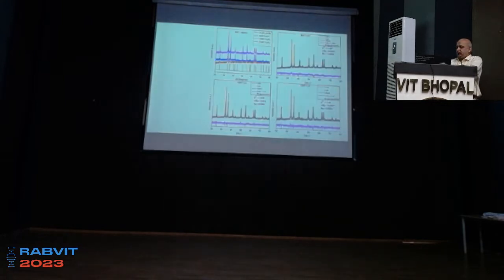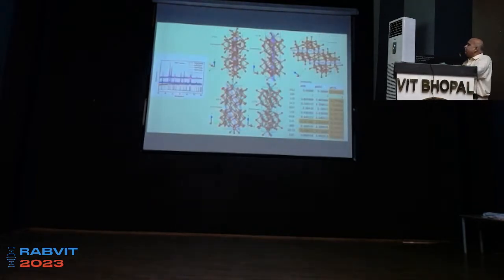Now, so this is the exciting part. Okay. So we started putting our mind into what exactly is different in S10. And what we found is that the different planes have different intensities. So what is the change between one sample to the other in terms of this intensity? We tried to find out. And why do we need to find out? We know that it is from the scattering factor. So are more atoms with these elements scattering more? That is what we are trying to find out.